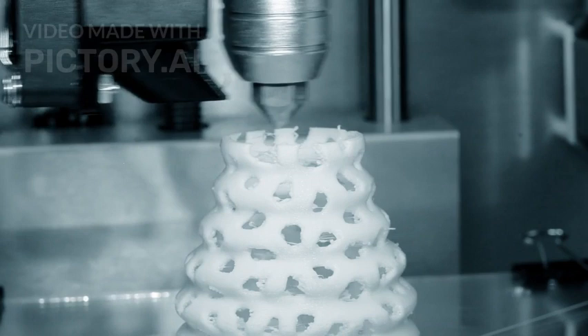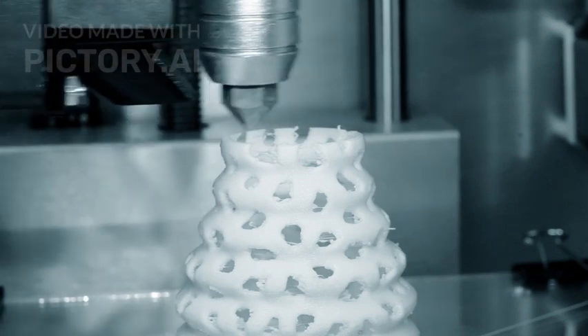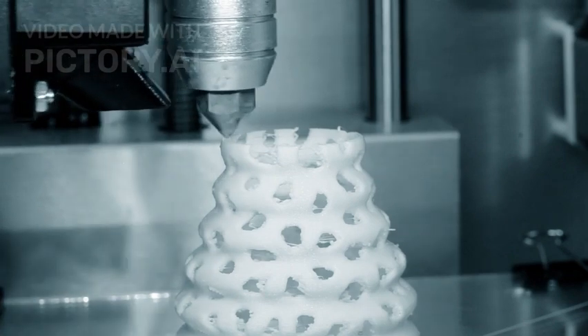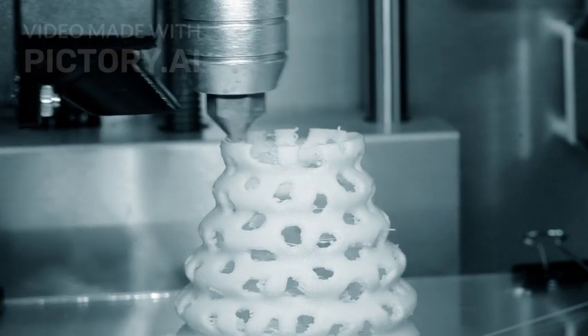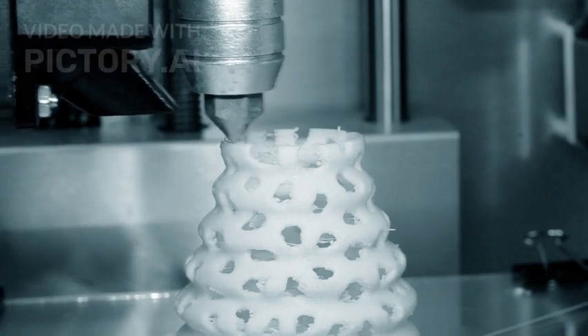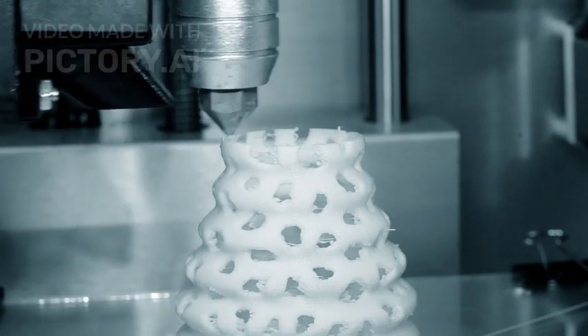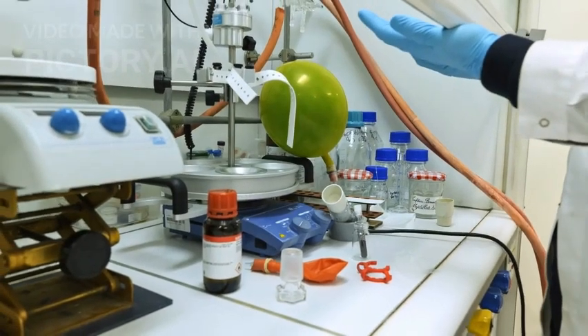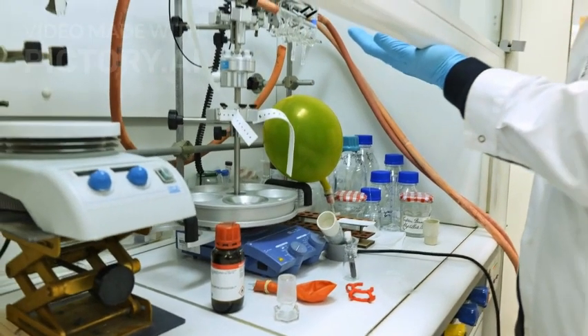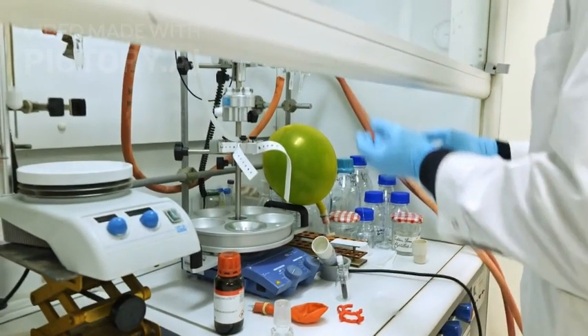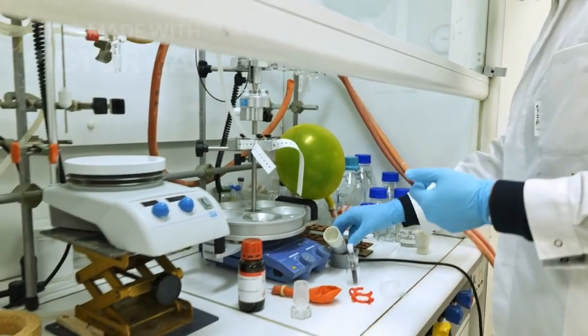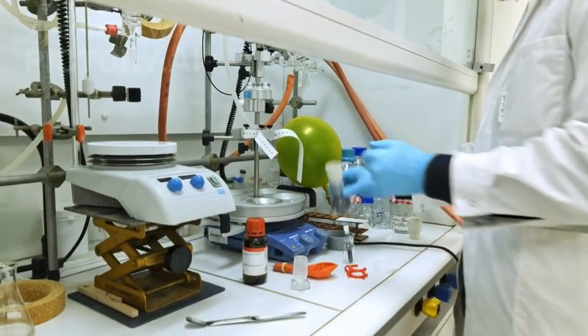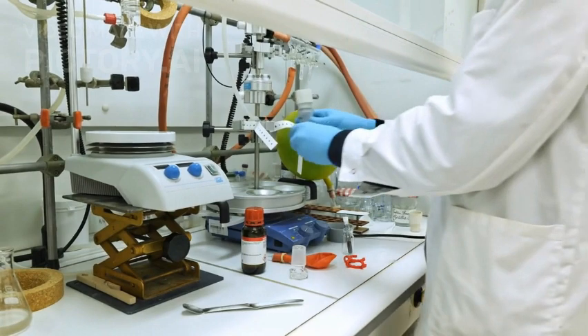And was it just about the peak strength? Or did it help in other ways? It wasn't just the peak strength, no. The mechanical integrity after the initial cracking started was also vastly improved. Think about it. Even if a ceramic rod breaks, the polymer filling the space around it can still hold the pieces together, bridging the gap. So it stops it from just crumbling apart immediately. Exactly. The infiltrated structures could still bear a significant load even after some damage.